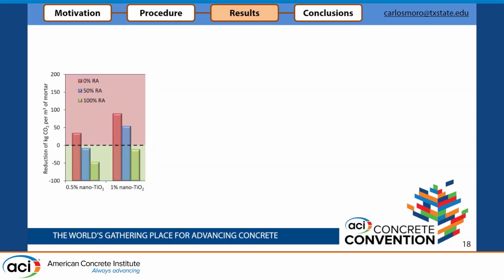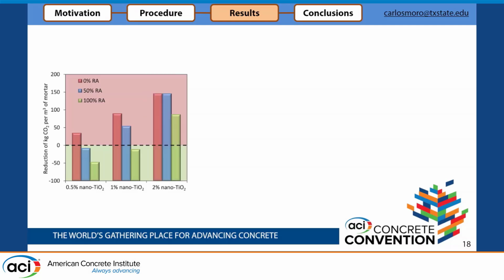If we go further with higher percentage of nanoparticles, the results show similar effects to what we saw before whenever we were comparing the global warming potential directly, that basically if we use a higher amount, maybe it's not as useful or as beneficial anymore. And we have higher emissions, for example, with the 2% compared to the reference samples. However, as I mentioned at the beginning, system boundary is a key thing here, and this is a cradle-to-gate. That means that we are basically producing the mortar and then we are stopping there. That means that we are not using any effects that this material has later on.